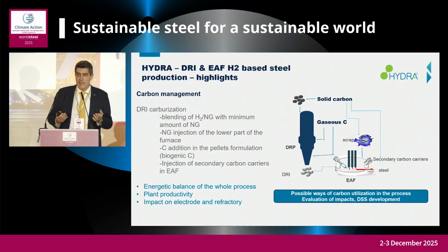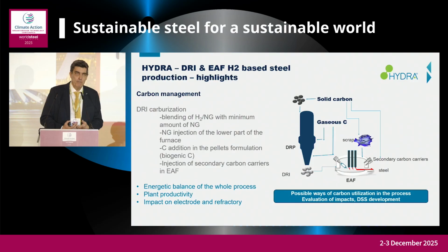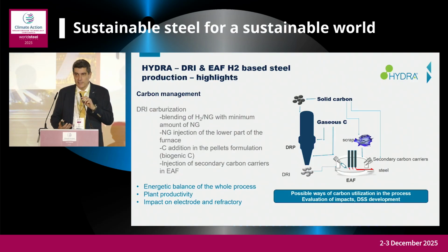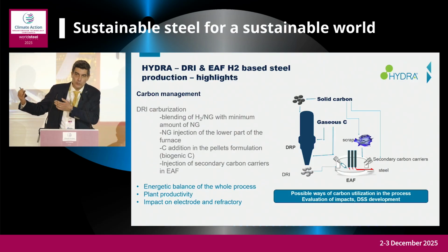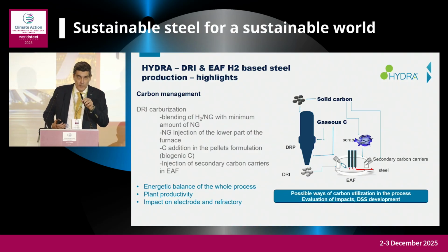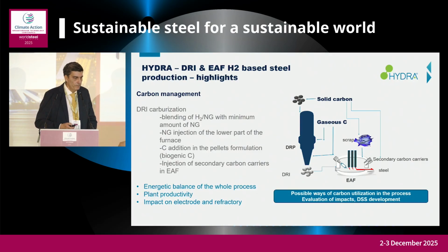So if you obtain DRI with a lower metallization degree, just as a very basic example, you will consume less energy and less gas in the reducing step, but you will consume more energy in the electrical furnace. So you need to understand where the break-even is. That is not always the same for all types of production. And in this sense, I think that the possibility to have experimental facilities and also fine-tuned modeling to give those types of responses is essential to manage these issues.